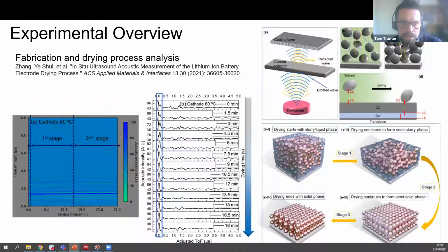And we can also use the acoustic response in some of the formation and fabrication processes. As electrodes are drying out, their material properties are changing, and we can track these peaks, which we believe are multimodal. So we believe that as the material is changing, we have these modes of acoustic wave propagation occurring through the electrolyte and then through the solid. You can see that as they're definitely two separate phases, there's two peaks, and then as it dries, the solid becomes dominant, and more or less all of the connected pathways are through the solid, and you just have this one peak.